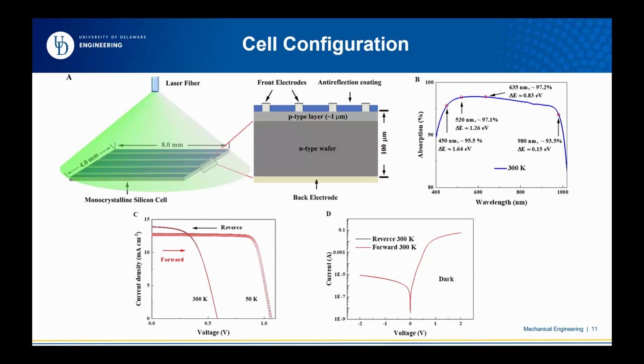Okay, so the idea is to distinguish what the dominant, main determining factors are. We apply lasers, a single wavelength of light at the beginning, and later we use the full spectrum. Here is the setup. The cell, we didn't produce ourselves. We bought a commercial one, okay? So there's no trick there. Just a commercial one, an N-type, and you can see the total thickness of the cell is about 100 microns. We also apply four types of wavelength lasers: 450 nanometers, 520 nanometers, 635, and also 980.